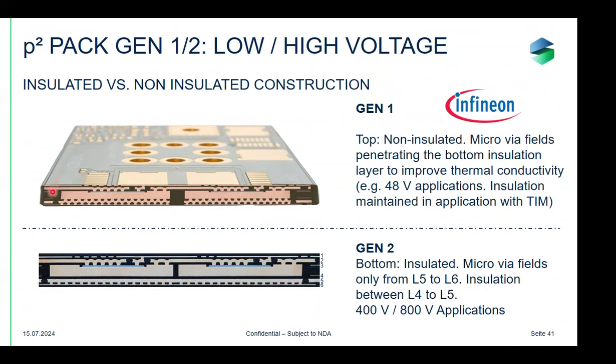So what you see here, generation 1 is a non-insulated version. On the back of the standard cell, you see two levels of copper-filled vias. That means you have the drain potential also on the backside of the PCB. For 48-volt applications, this is not a hassle, because this insulation that you need to the heatsink can be easily maintained with a thermal interface material that has to be placed anyway between the P-square pack and the heatsink to carry the excess power losses from the component to the heatsink.